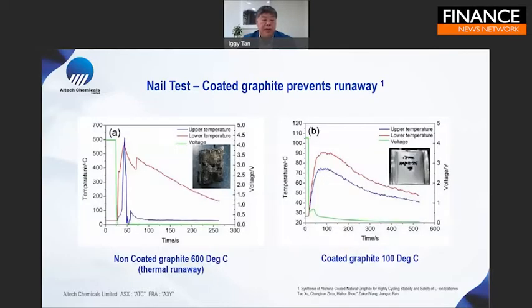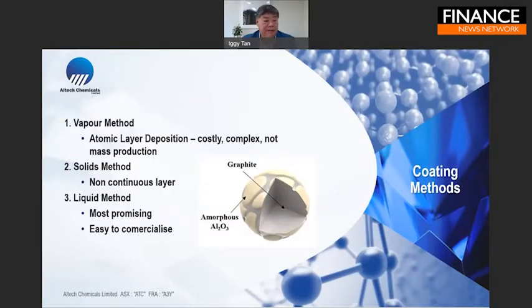I did mention thermal runaway. This is another test that has been done by various groups where they do a nail penetration test. On the left-hand side, you've got a non-coated graphite. The temperature skyrockets to 600 degrees, and virtually the battery catches fire. On the right-hand side is a coated graphite battery, and the temperature goes up to only 90 degrees, and essentially it remains intact. So graphite coated with alumina also helps with the safety of the battery.